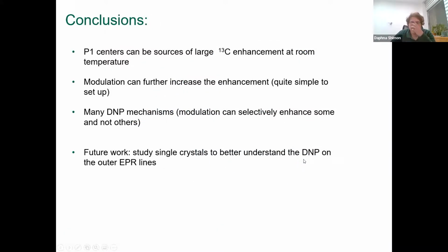So I just want to conclude and say that we show that P1 centers can be sources of large carbon-13 enhancement at room temperature. And what we're seeing is enhancement of about 70 without modulation and even over 100 when we add modulation. And modulation is pretty easy to set up with just an AWG. And so it's not so hard if this is the kind of experiment you want to be doing.